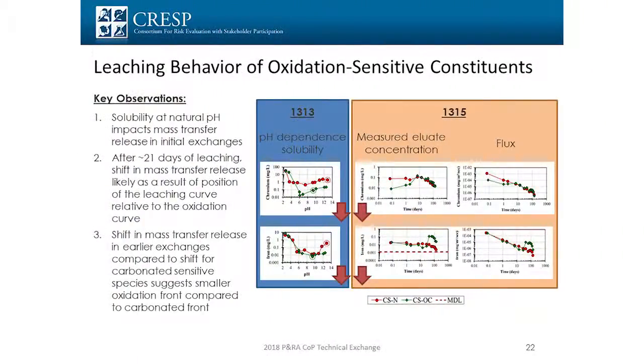For oxidation-sensitive species, and again, this is chromium and iron, you'll see, again, an effect on the natural pH. Again, it affects the initial mass transfer release. And then you'll see after 21 days for this, you'll see this shift in the mass transfer. And that's, again, the relative position of the oxidation front to the leaching. And the shift that you'll see in the mass transfer in the early releases is, we suggest, the fact that the oxidation front is moving more slowly than the carbonation front in these materials.